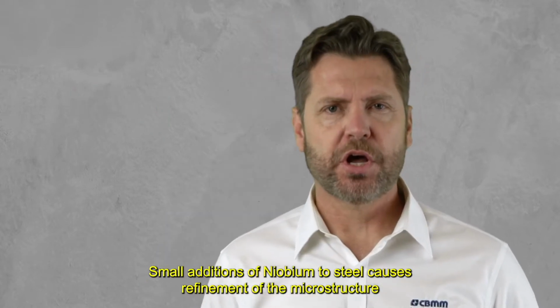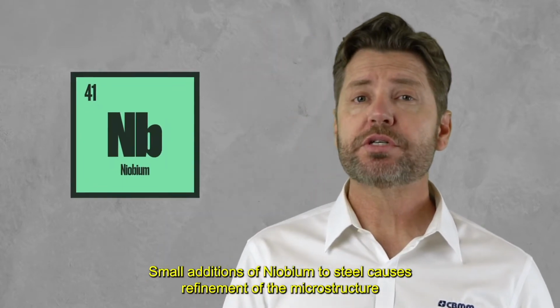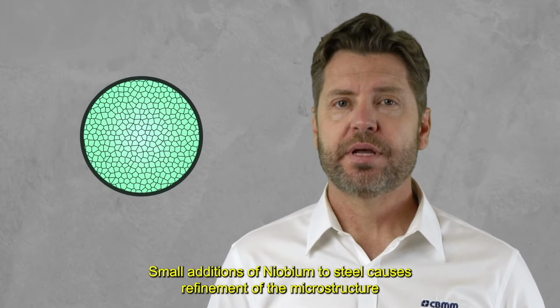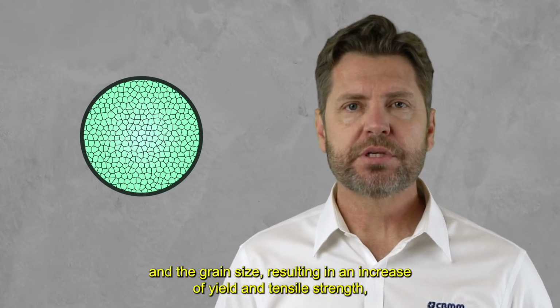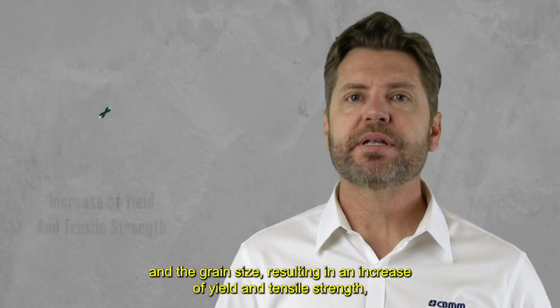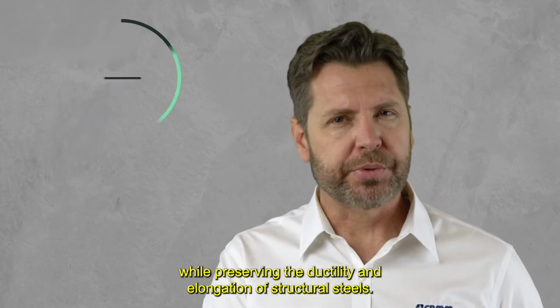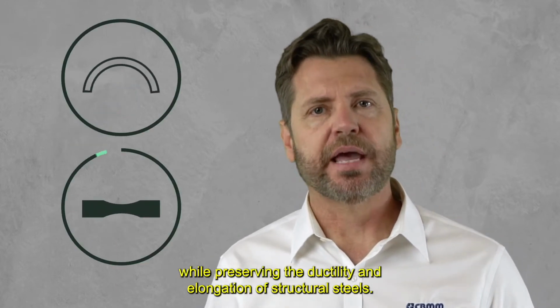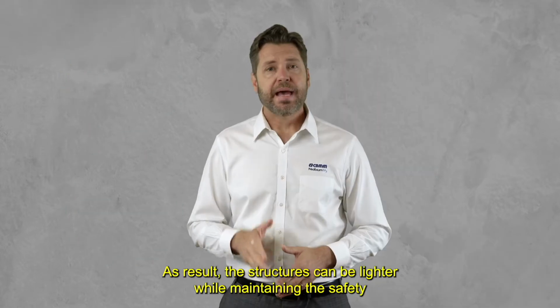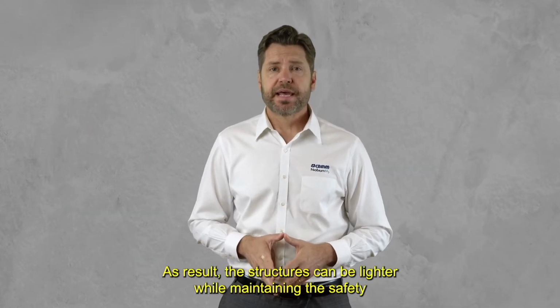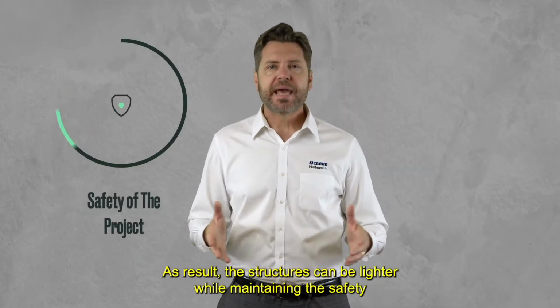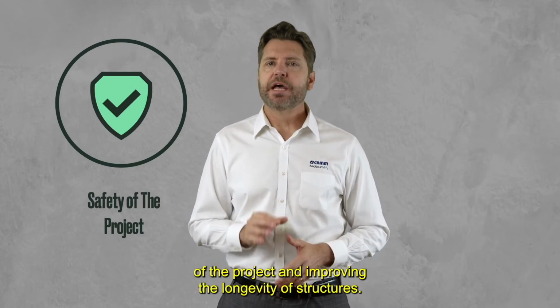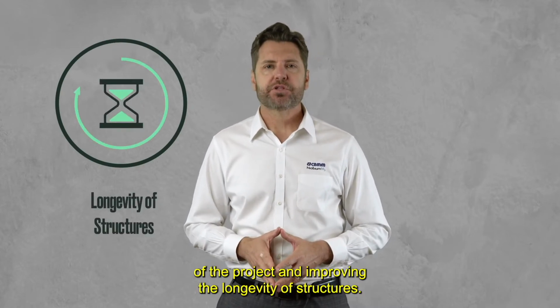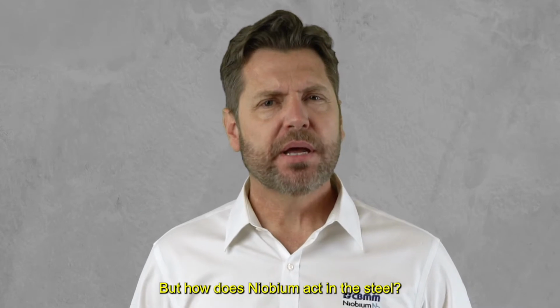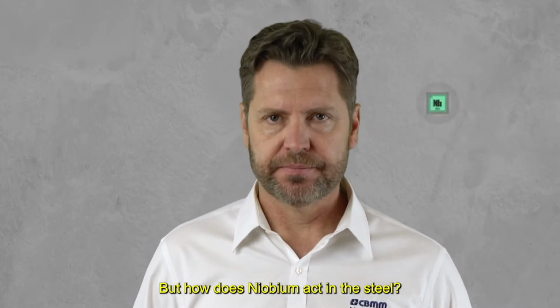The small additions of niobium to steel cause refinement of the microstructure and the grain size, resulting in an increase of yield and tensile strength, while preserving the ductility and elongation of structural steels. As a result, the structures can be lighter while maintaining the safety of the project and improving the longevity of structures. But how does niobium act in the steel?